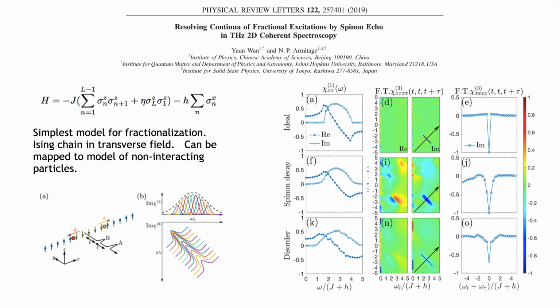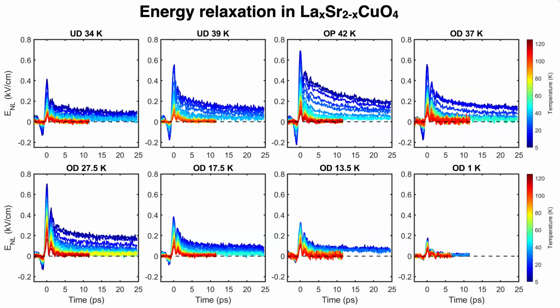I'll say one more quick thing, and again, just kind of flipping through some of the stuff. One of the things we've been working on now is looking at what we call the energy relaxation rate. And the energy relaxation rate, this is in lanthanum strontium copper oxide, but we've done a variety of different materials. And in lanthanum strontium copper oxide, we pump the system, and these other metals, we pump the system. We look at this pump probe response, which I mentioned, and then we look to see how the system decays afterwards.